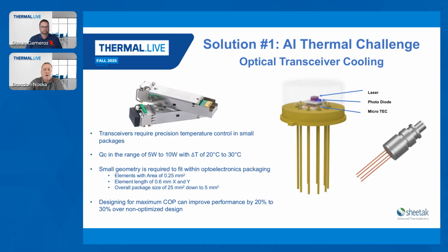And so often these TECs require leg geometries that are 0.2 or 0.3 or 0.4 millimeters in X and Y dimensions, and as thin as maybe 0.25, 0.3 up to say 0.5 or 0.6 in height. So very small leg geometries and typically lower couple counts, something like 8 couples, 12 couples, or 16 couples, operating at lower voltages, and the current can be tuned, as I mentioned before, to match the cooling power required for the application.